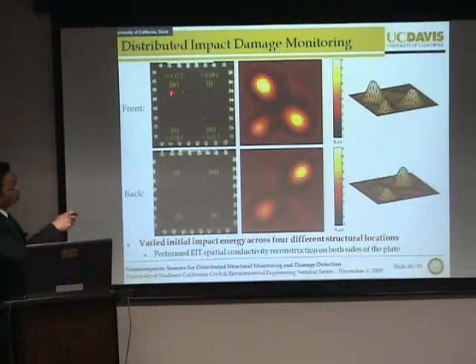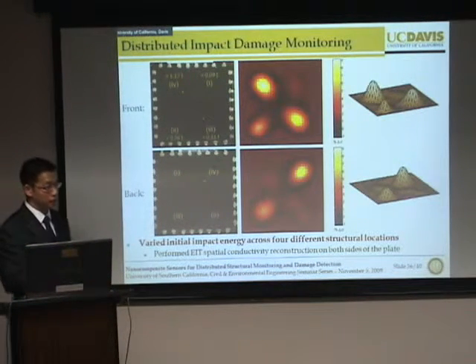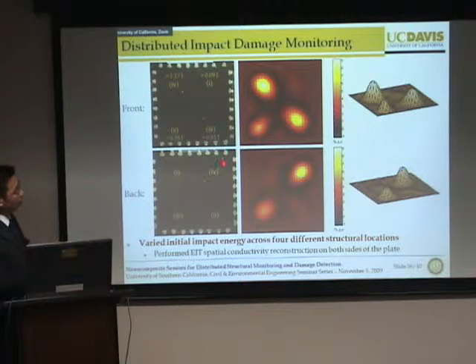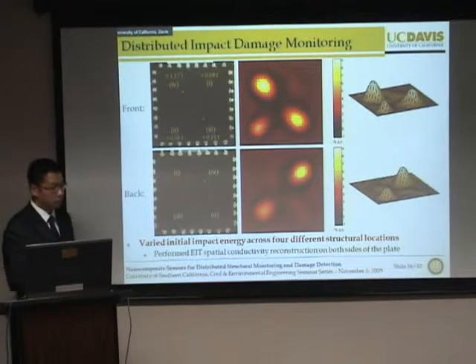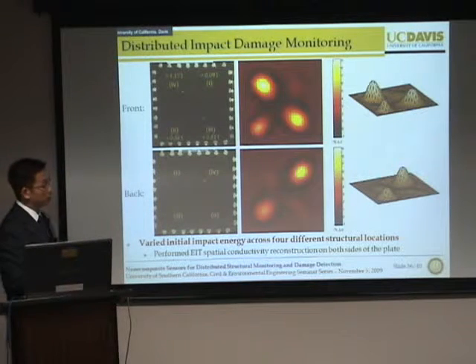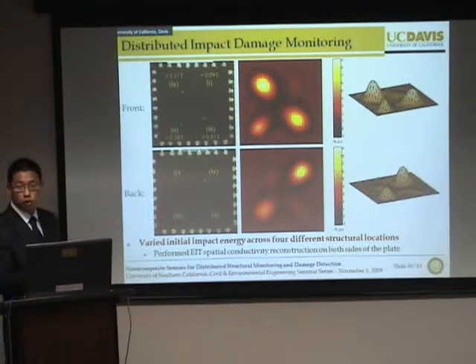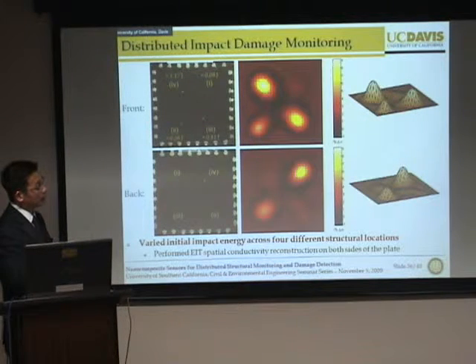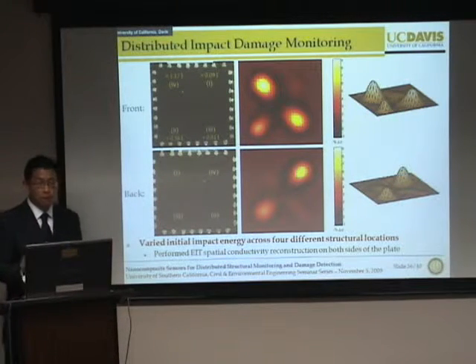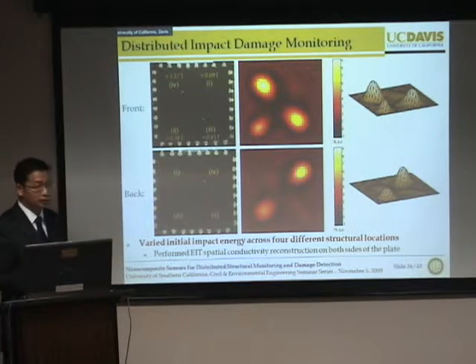Now, upon impacting our plate at 4 different locations with 4 different impact energies, where 1 corresponds to the lowest energy and 4 corresponds to the highest impact energy, and here we're looking at the same piece of material, but one from the front view and one from the back view, where the back view is where the impact hammer directly strikes your plate. We can then run this EIT algorithm on our sensing skin and basically map out the 2-dimensional conductivity of our material, where you see that regions where you have impact damage light up on this conductivity map. And the change in color corresponds to the change in conductivity, which also correlates to the magnitude of damage.